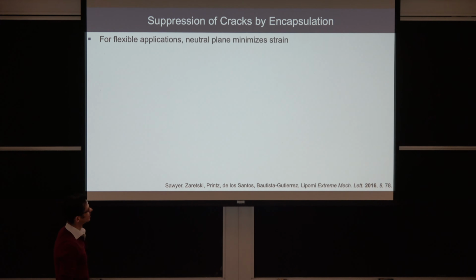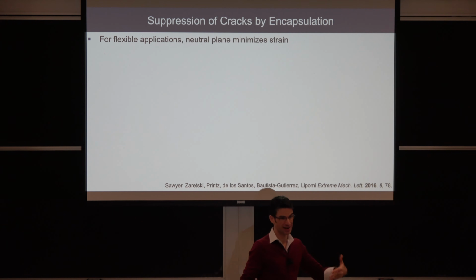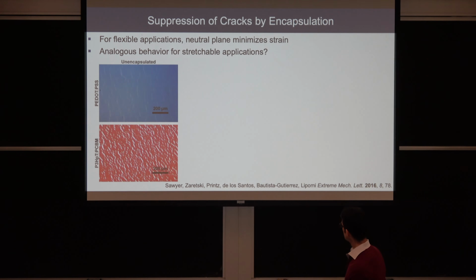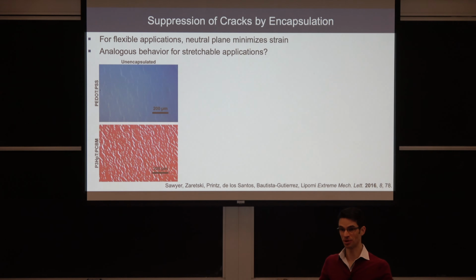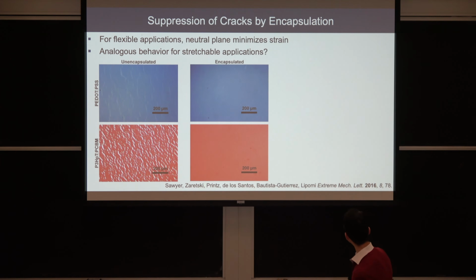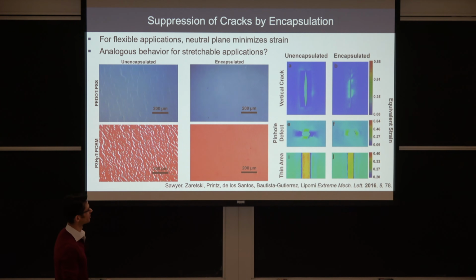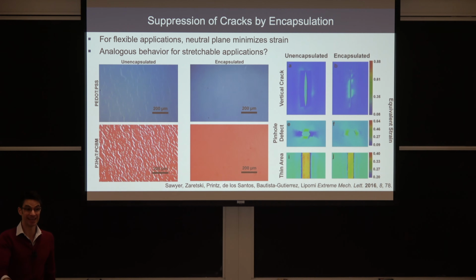Now sometimes you can prevent cracking by encapsulating the material. So what happens when you stretch these materials to 50% strain on an elastic substrate, you get all these cracks. Our hypothesis was if you put another layer of elastomer on top, you can redistribute strain energy and suppress the formation of cracks, and that's indeed what we see. So these are some finite element models, sometimes called rainbow diagrams, which show you that encapsulated films, if they have pre-existing defects in here, concentrate stress and strain to a lesser extent than those that are not encapsulated. So we don't always need to change the molecular structure or the microstructure. Sometimes just the device layout can give us what we need.